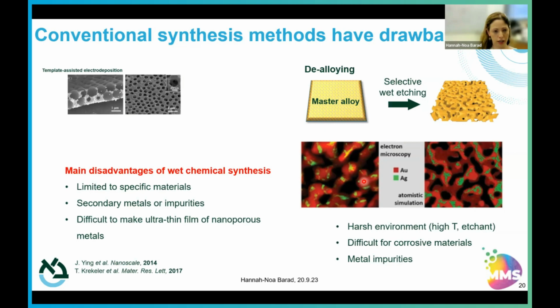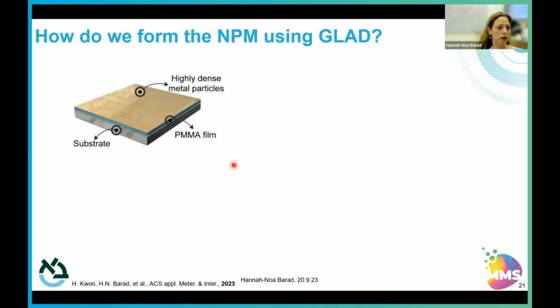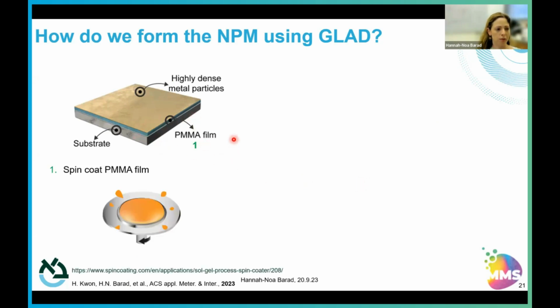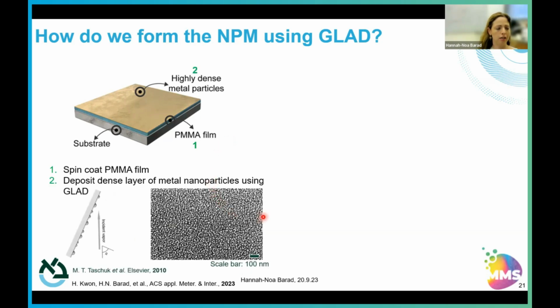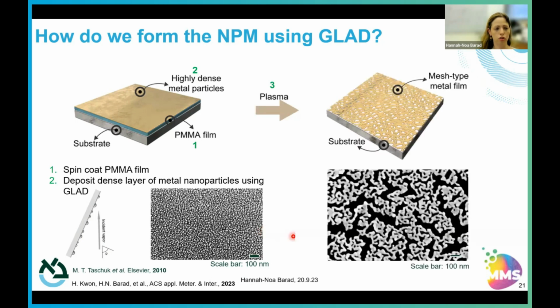So what did we do here to try and solve this? We start out with our substrate material, on top of which we deposit a PMMA film just by pure spin coating, very simple. This is a thin film, several microns thick. On top of this, we do glancing angle deposition. And the benefit of glancing angle deposition over here is that it forms a very high density layer of nanoparticles. So these are maybe 20 nanometer nanoparticles, no more than that, of course, even smaller ones. And then the next step is we do some sort of plasma etching, and we actually end up with these nanoporous metal films. So these nanoporous metal structures.